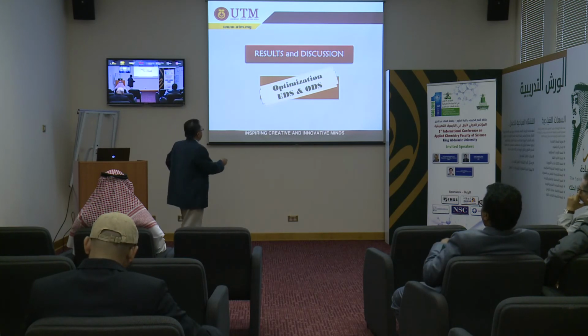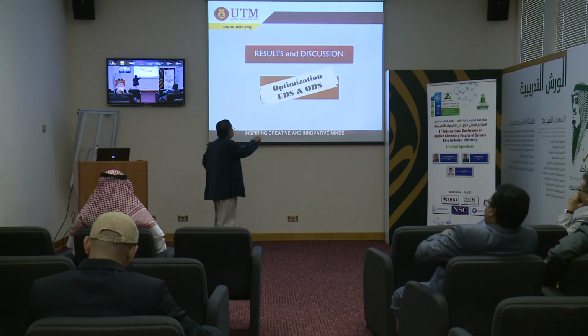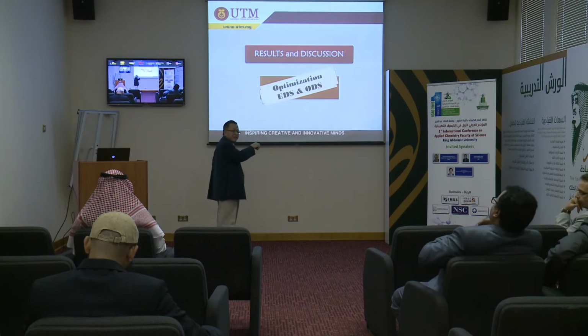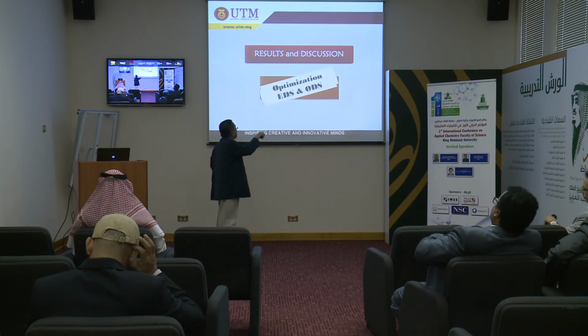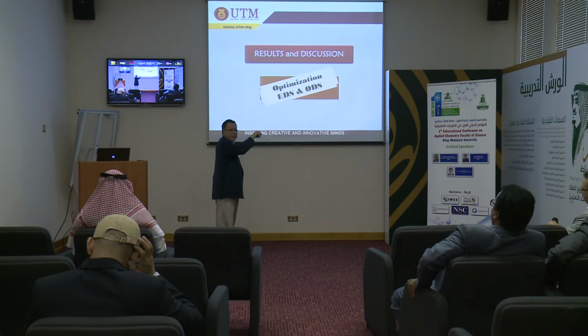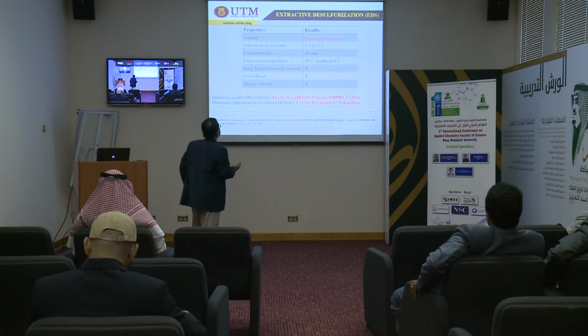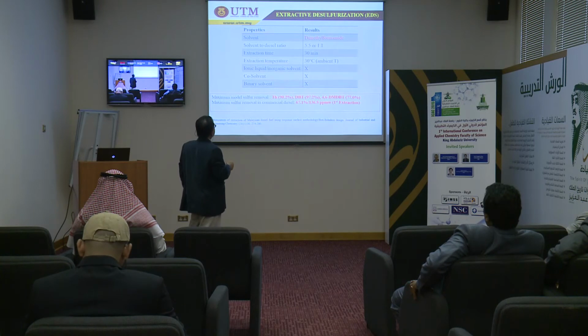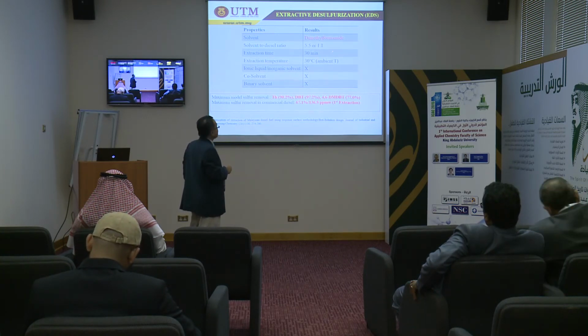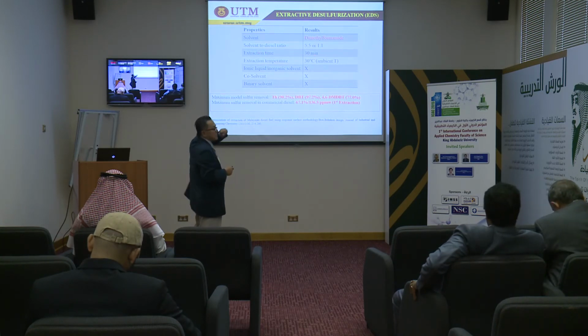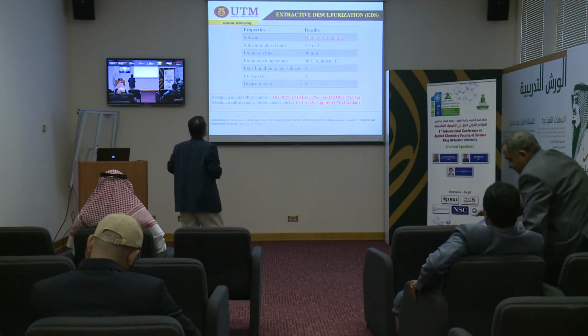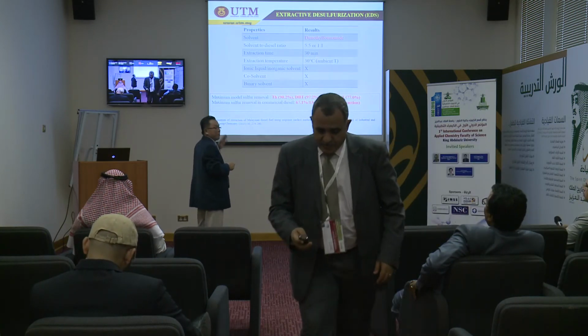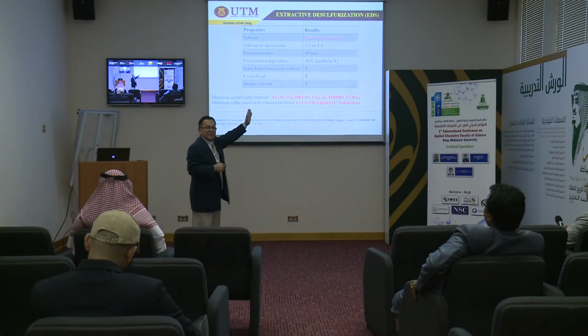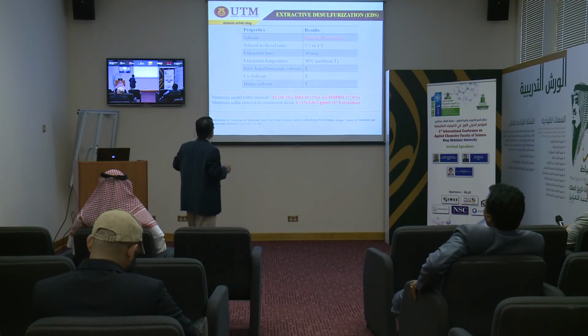Just have a look at these optimizations of EDS, I mean solvent extraction only with the diesel, and ODS, the oxidative desulfurization technique. This is the result. We use solvent DMF, solvent ratio 1:1. For extraction we just shake it 30 minutes. For temperature, in fact we have tried 20, 40, and this one is the recommended.